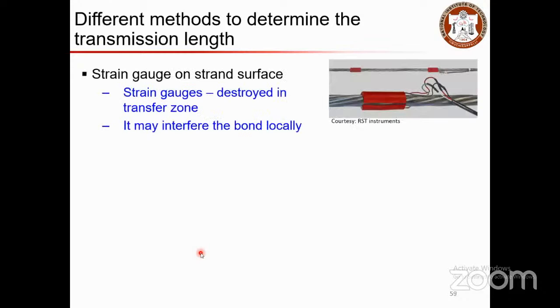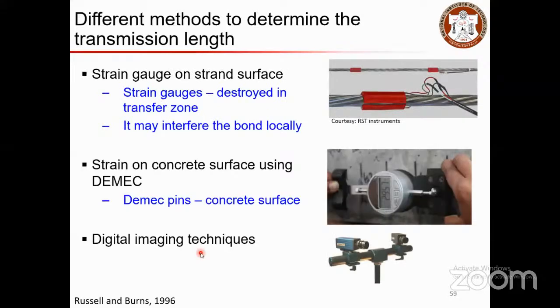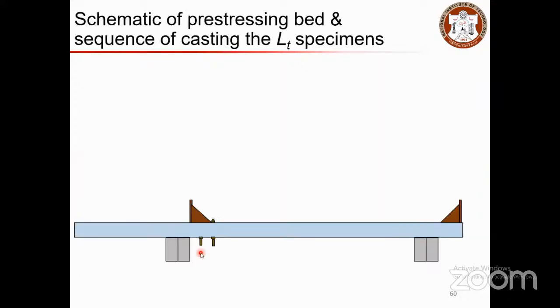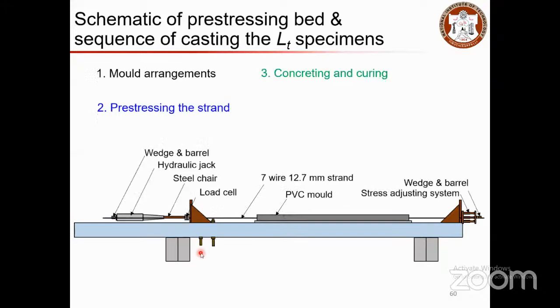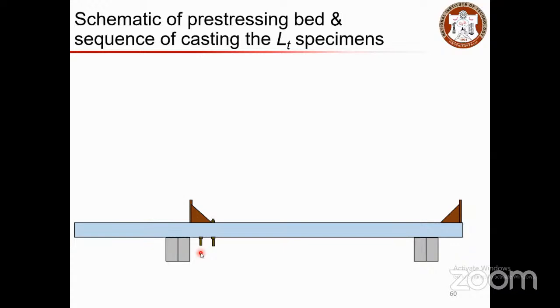And I'm talking about the transmission length. I'll tell you how to measure the transmission length also. Basically, you are measuring the strain on the concrete surface. That would be using strain gauges or using Demec pins or using DIC techniques. So from this, you measure the change in distance and then you calculate the strain and you plot the graph. I'll just illustrate the sequence of the process used to prepare these specimens.